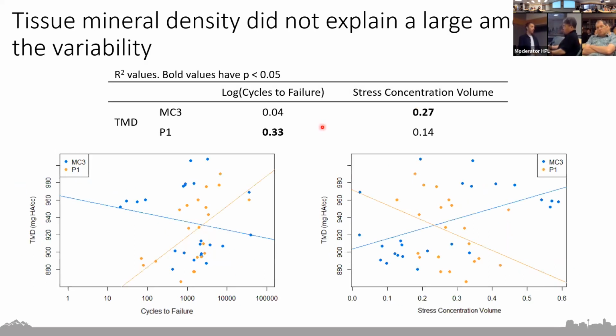So one thing we looked at was the degree of mineralization, the tissue mineral density. And we found there were some relationships, but it didn't explain a huge amount of the variability. So this suggests that this difference isn't necessarily explained by the degree of mineralization in these samples, but can probably be attributed more so to differences in the microarchitecture.